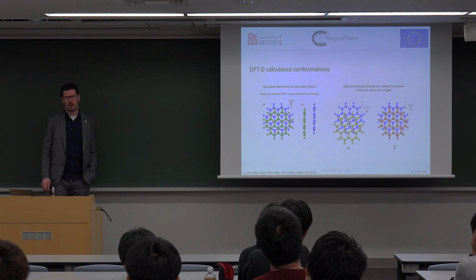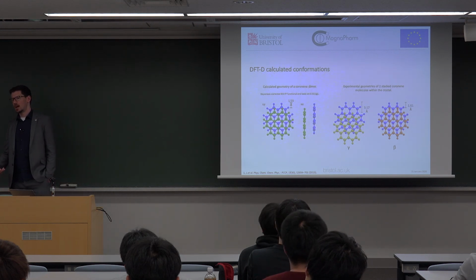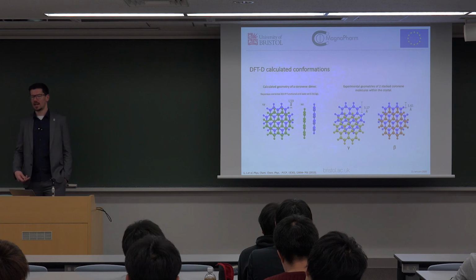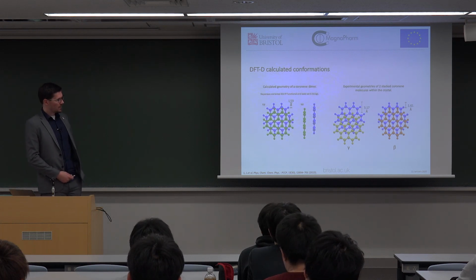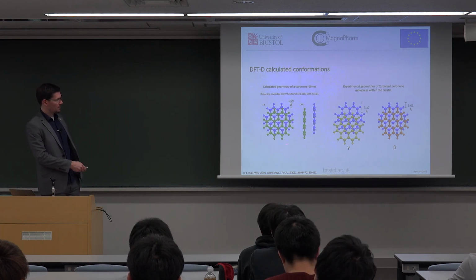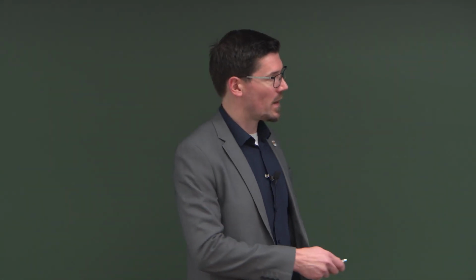If you take 2 coronene molecules and minimize their energy in a vacuum, you get this overlap here, an offset by 1.59 angstroms. This has been done repeatedly in the literature. I've redone it myself. It always happens this way. This offset is always the way in which coronene sits when you've got 2 molecules together. Even if you calculate a cluster of 3, 4, 5, 10, there's always this offset between neighboring molecules.